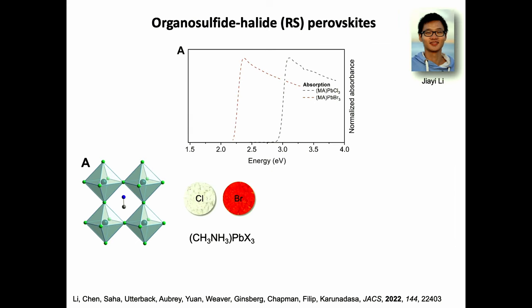If you look at your standard halide perovskite, a chloride and bromide, these are photos of the perovskites. You can see that the chloride is colorless and the bromide is this beautiful red-orange, and that reflects the changing band gap, right? As I mentioned, the halide can tune your band gap. So if you have a chloride, you have a very large band gap. If you go to a bromide, your band gap redshifts quite a lot. And this is kind of unfortunate because I think it's almost a general rule in materials chemistry that the more interesting your material is, the less stable it is. And likewise, the chloride is very stable, but the band gap is way too high. And as you go to the iodide, things become more interesting and less stable.